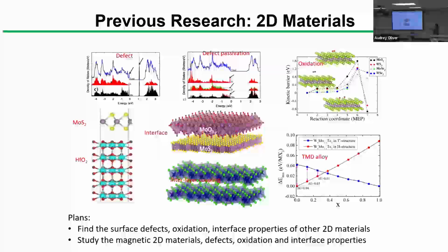So using DFT, we can predict those properties. And we can also create defects and see where those defect levels are. So it may have various applications. Sometimes defects are desired, for example, in the quantum information area, right? So we can use those defects. This is not the best material for quantum information, but a similar technique we can use. And for semiconductors, as a channel material, we don't want defects. In that case, we can do passivation. We can find out which species can passivate that defect, right? So we can remove that dangling bond.